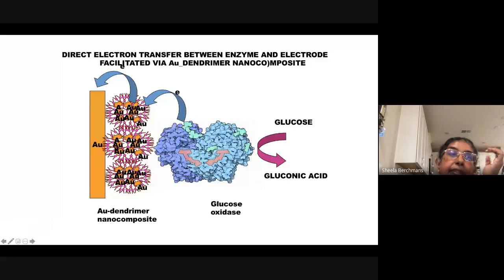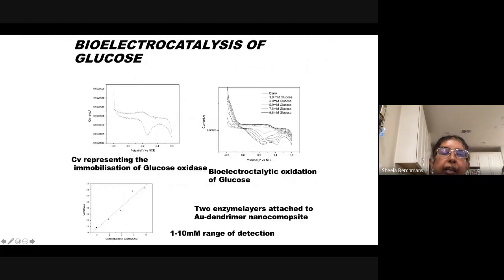So making use of this polyamidoamine amine-terminated dendrimer molecules, we encapsulated gold nanoparticles inside the dendrimer molecule. Then we attached the glucose oxidase enzyme, which converts glucose into gluconic acid on oxidation. Initially, we tried it as a biosensor. Making use of this Au dendrimer nanocomposite, we can sense glucose in the range of 1 to 10 millimolar.